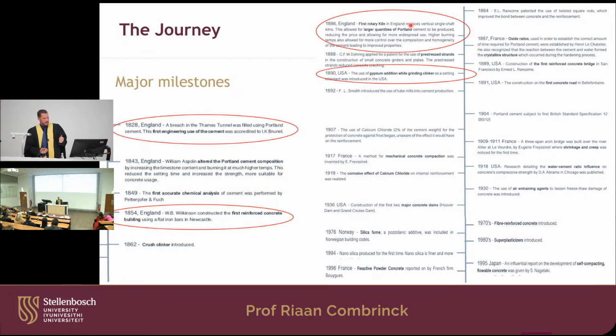Then another aspect of it was when gypsum was added to concrete. Now, if you just have normal Portland cement and you add water to it, it hydrates very fast, and then you don't have fresh properties that you can actually cast it and vibrate it and so forth. So in the beginning, when they used concrete, they needed to be quick. It hydrated and set very quickly. But when they added gypsum, the gypsum retarded the setting time, and it allowed you about 3 to 4 hours that you can work with the concrete while it's plastic, and cast it and compact it perfectly. So this was also a very big milestone.